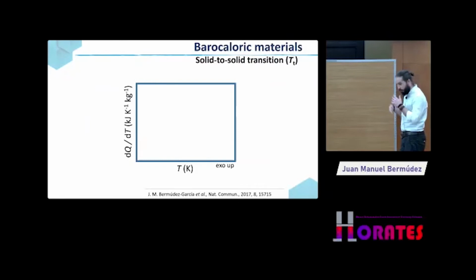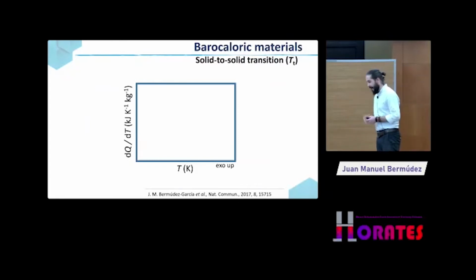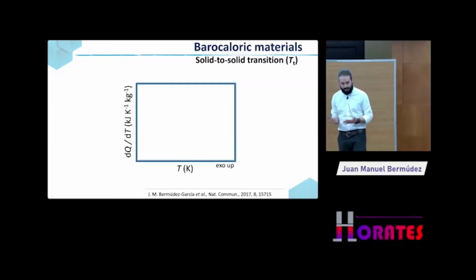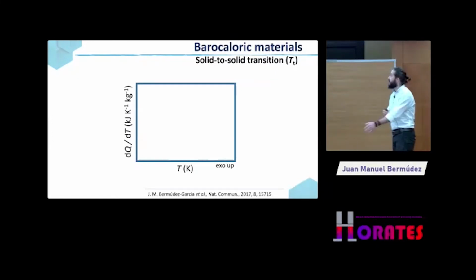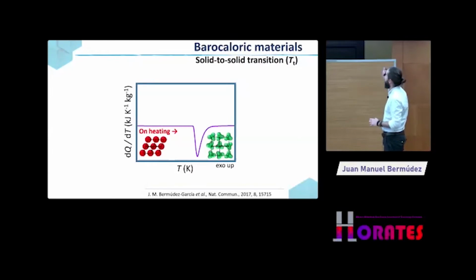Well, how do we characterize all those parameters? As Matt explained before, the main technique for characterizing the thermal properties of these barocaloric materials is going to be differential scanning calorimetry. As he already explained this technique, I'm not going to go deep into that, but basically you register the heat flow of your material, the heat that is exchanged by your material, like releasing heat or absorbing heat upon the transition, right? And for that, you can study the material by increasing the temperature. So first, you start in a low temperature phase, you increase the temperature of your material, and at some point, this material transforms into a high temperature phase. And this transition is going to be endothermic, okay?